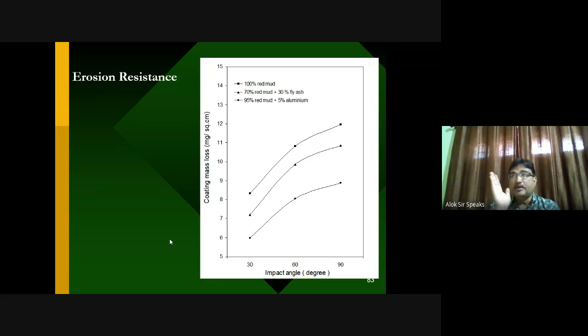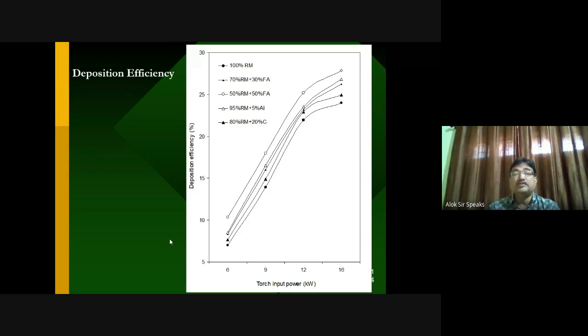Then erosion resistance. Erosion is a particular wear mode which occurs in dusty environments and causes a lot of degradation to the component. Our purpose was to make erosion resistant coatings. Therefore, these coatings were subjected to an erosion test, and we found that the red mud coatings have fairly good erosion resistance and can be used for erosion resistance purposes. The deposition efficiency was not very high, but in the plasma spray world, 25 to 30% is considered good. We got a maximum of around 27-28% deposition efficiency, which says what fraction of the powder that you are feeding is getting deposited on the substrate. That is deposition efficiency, and it is very relevant and important from an economic point of view for spray grade expensive powders.